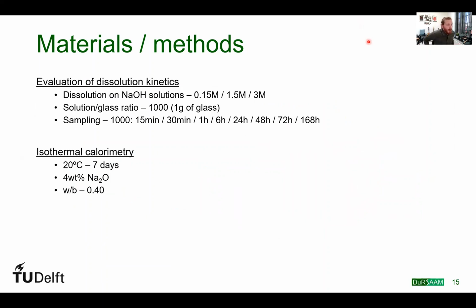The experiments that we performed were dissolution experiments in highly diluted systems with sodium hydroxide at 3 different concentrations, a solution to glass ratio of 1,000 using 1 gram of glass. We took samples from 15 minutes to 7 days. We also performed isothermal calorimetry to correlate both experiments, at fixed temperature, fixed sodium content, and fixed water binder ratios.